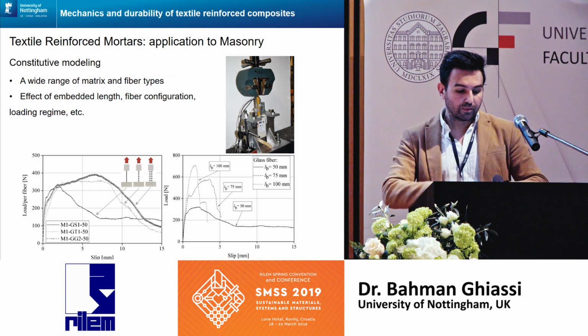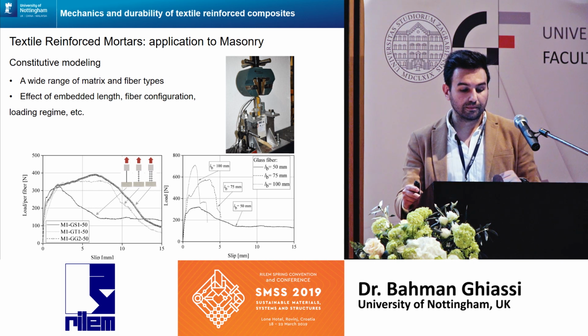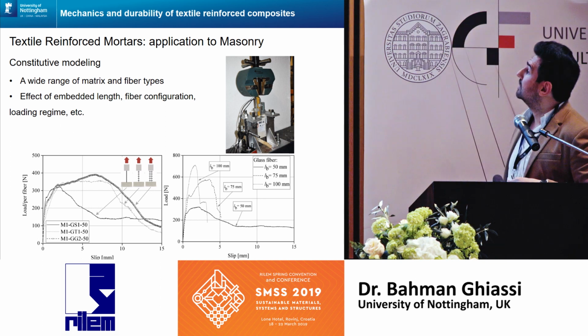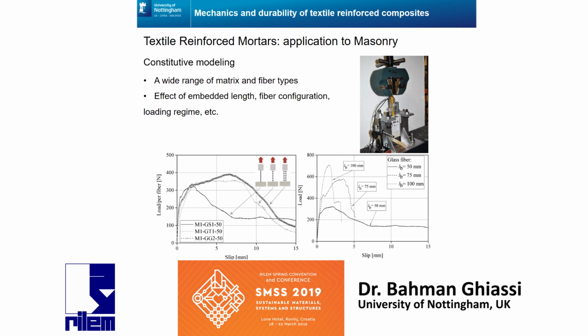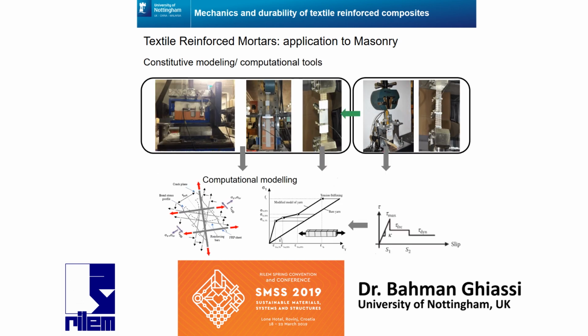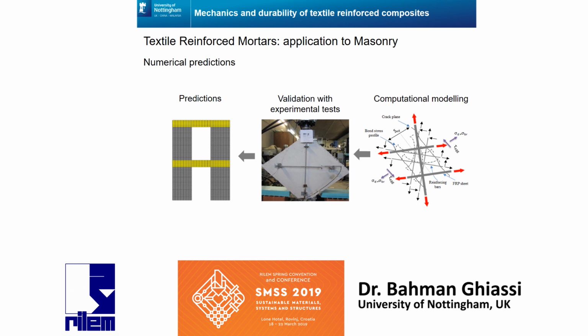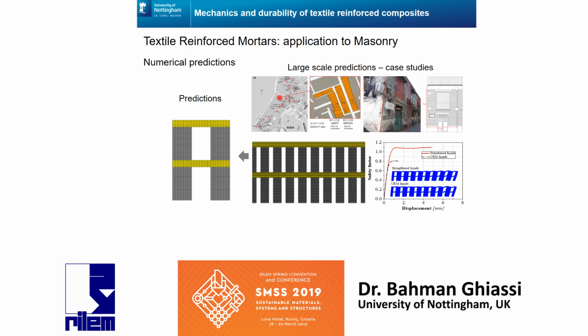So having a wide range of testing on different combinations of fibers and mortars, we developed constitutive laws for the pull-out response of the fiber to mortar behavior, and then we use that for upscaling to the tensor response, and then validating it with experimental tests, and then using that information as the input of a computational model that can predict the response of structural elements strengthened with these materials. And then our predictions were not only at the single building level, but we also went a little bit larger and at the more global scale. And today we can predict the response of masonry facades, large facades strengthened with these composites.